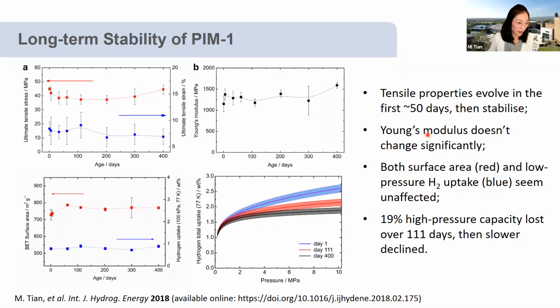So the mechanical property shows this feature. They fluctuated in the first 50 days and then stabilized. But surface area and low pressure hydrogen uptake seem unaffected, which is really good. But the high pressure properties declined slowly, which is a problem for pure PIM1 film. But then we found introducing porous fillers greatly improves its long-term stability. We are carrying out this study at the moment, but to be honest, nothing changed. So the figure is pretty boring, so I didn't show it here. So introducing porous fillers has a positive impact on the aging of the material.